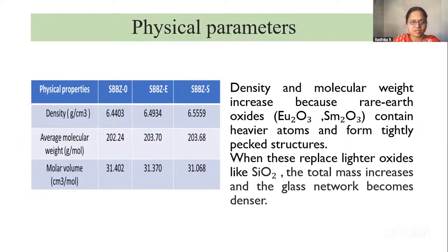doping with europium, it is approximately 6.49, and doped with samarium, 6.55 grams per cubic centimeter density we can observe. Easily we can understand that the density increases by adding the rare earth ions, and also the average molecular weight increases by adding the rare earth elements, and molar volume decreases.